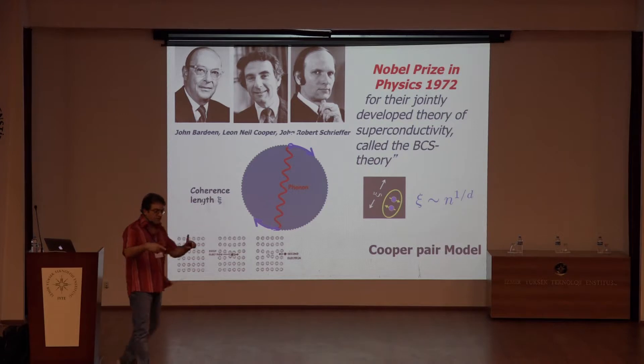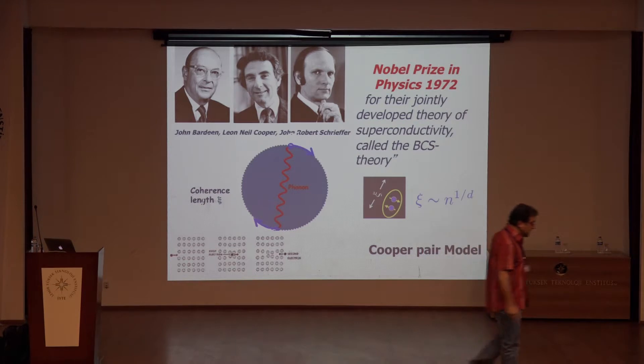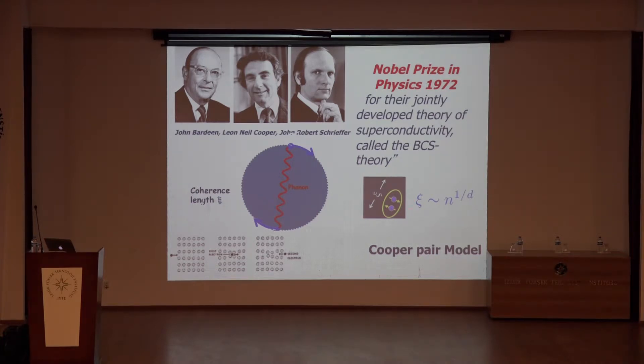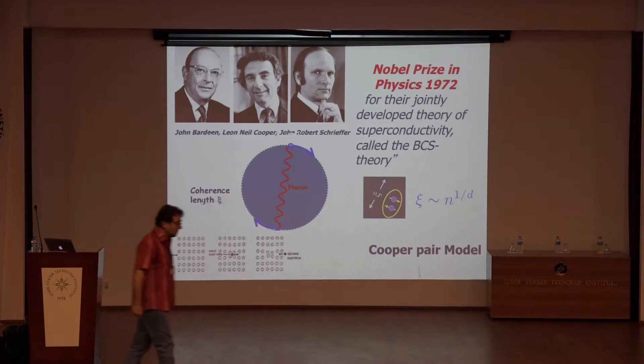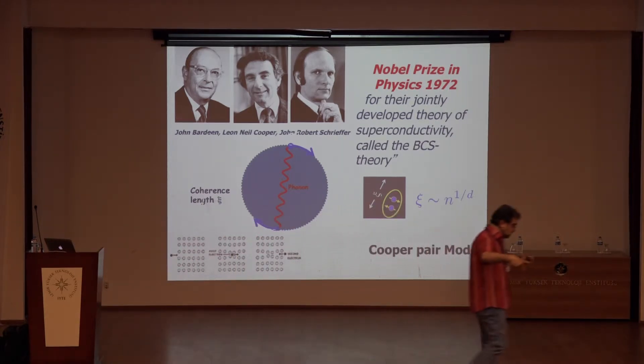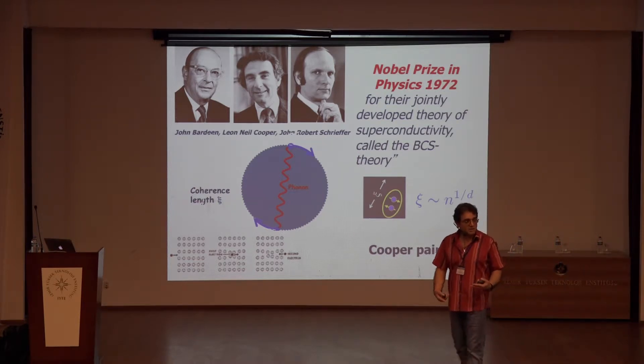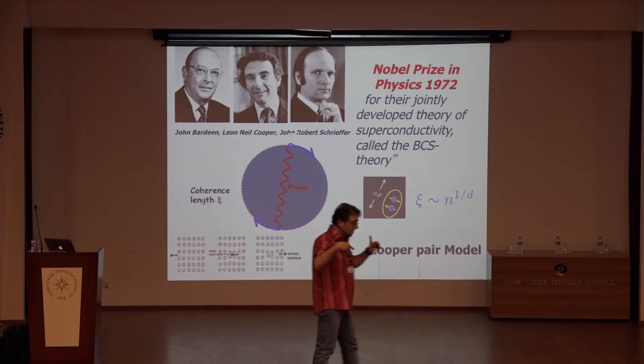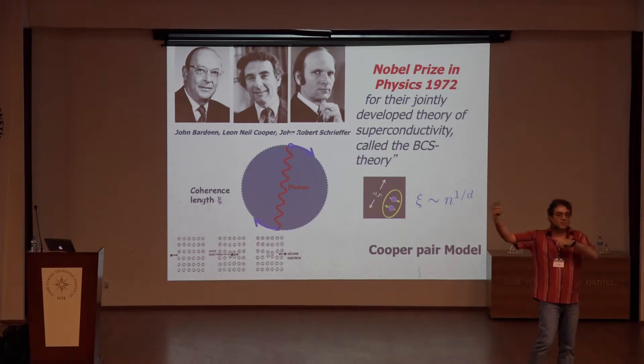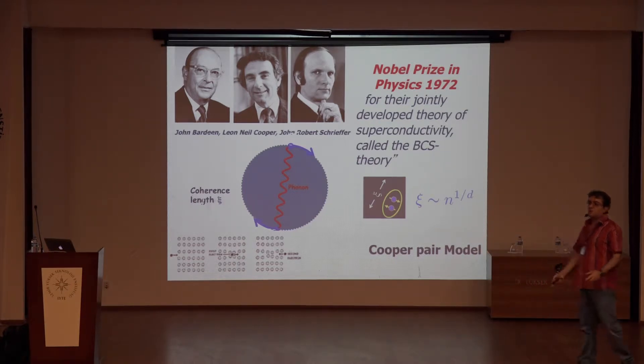Two electrons can attract each other, but notice they can be very far from each other. The distance between two electrons — the coherence length — is proportional to the electron density to the power of 1/d, where d is dimensionality, and this could be very long, up to 10^4 angstroms. Therefore we cannot describe superconductivity simply as Bose-Einstein condensation, since the two electrons forming a pair are far apart and we cannot use BEC models to capture the physics.